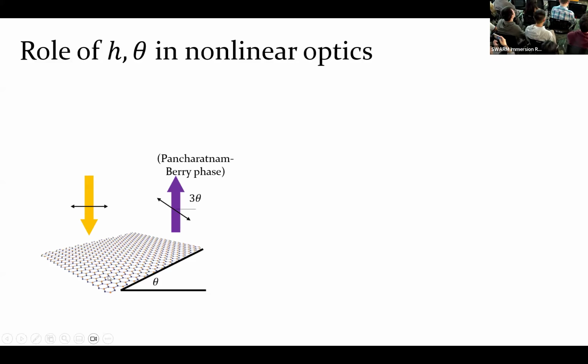But if the HBN is twisted by some angle theta, then the outcome of this second harmonic generation is also rotated by an angle that equals 3 times the twist angle. Okay, and the number 3 here comes from the fact that these materials are C3 symmetric. So if you rotate the system by 120 degrees, it is exactly the same as before. And there is a name for physicists, it's called the Pancharatnam-Berry phase, for this kind of nonlinear process.